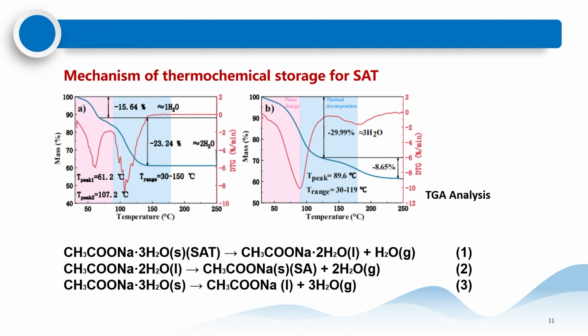And the mechanisms of the thermochemical storage of SAT, we also characterize with TGA, and we can see that when it melts, the water molecules remain inside the salt hydrate. However, when the temperature is above 100 degrees C, the water evaporates, and that provides an extra thermal storage than the PCM.